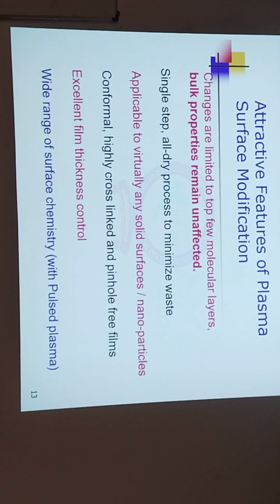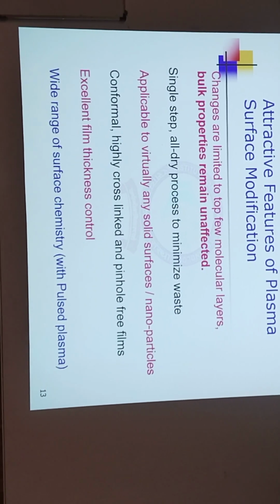So, the attractive features of plasma surface modification, these are the advantages, is that plasma can modify only the top surface layer, just a few layers, whereas the bulk property remains unchanged. That's the beauty of it. It is a single step, all dry process to minimize waste. So it means that it is an environment friendly process, applicable to virtually any solid surfaces or even nanoparticles with the 360-degree rotating reactor. The modifications which are carried out are highly conformal, highly cross-linked, and pinhole-free film can be obtained with the help of plasma polymerization, and we can have excellent control over film thickness. Whatever nanometer we want, we can have that specific. And a wide range of film chemistry is possible with pulse plasma. Next.